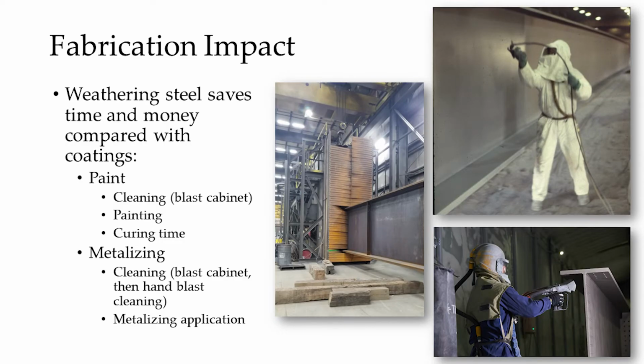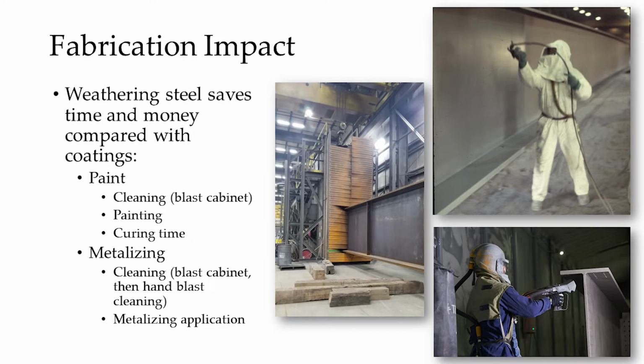Compared to metallizing, once again, you're cleaning. Metallizing requires a very significant cleaning. Metallizing, which is thermally sprayed on zinc, requires a deeper anchor pattern than paint. And so for metallizing, we'll first pass the girders through the blast cabinet, but then move them to another bay and then hand blast. So there's a lot of cost and time in cleaning for metallizing. And then the metallizing application takes longer than paint.